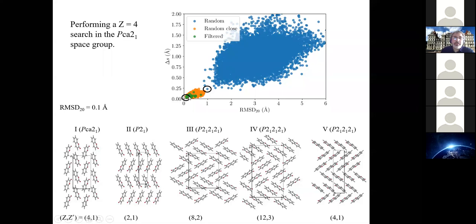So those are the orange ones. You do one less filtering based on trying to find the smallest value of delta S that you can. So you take the smallest orange one, you generate a new set of green ones, and then finally you get to a prediction, basically with a zero, almost zero delta S, right? And it turns out that you get the coumarin 1 structure this way with an RMSD20 value of 0.1, right? Without ever having to do a single energy calculation.